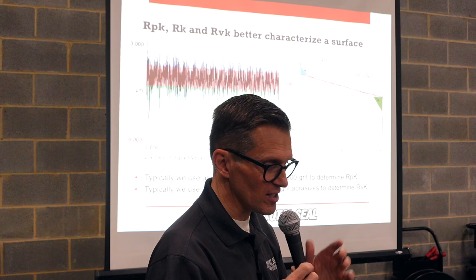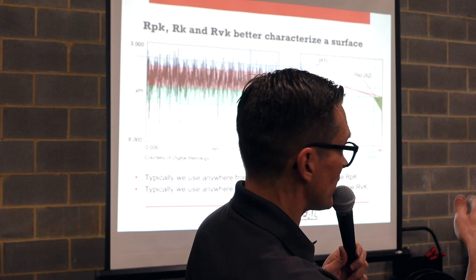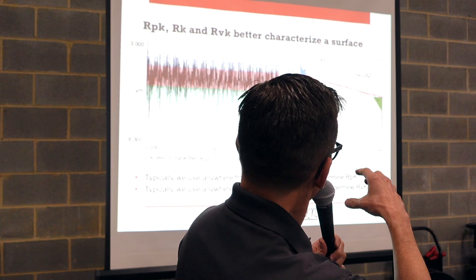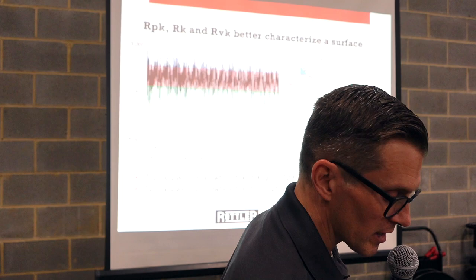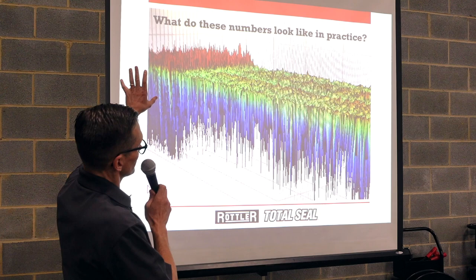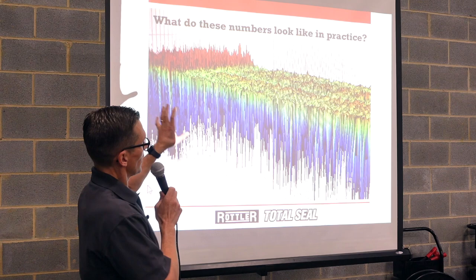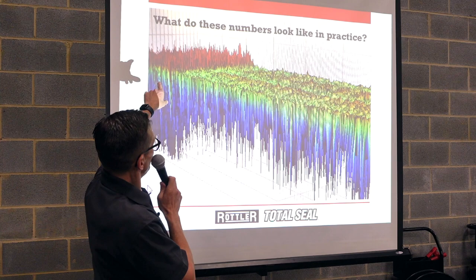So this is a little plot from a 2D, just a regular profilometer. But if you want to look at these numbers, the idea of the RPK, the RK, the RVK, and put it in practice and put it in 3D, here you go. So this is a 325 diamond single grit finish hone. And we're taking a 3D profilometer trace of just one section. Those big red peaks at the end, that's the unworn part. That's where the ring stopped. So imagine that's at the top of the ring travel, top of the cylinder, TDC.